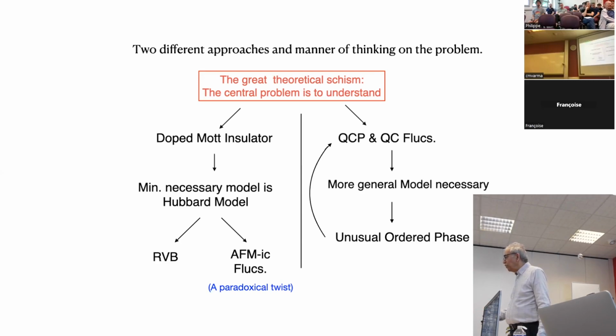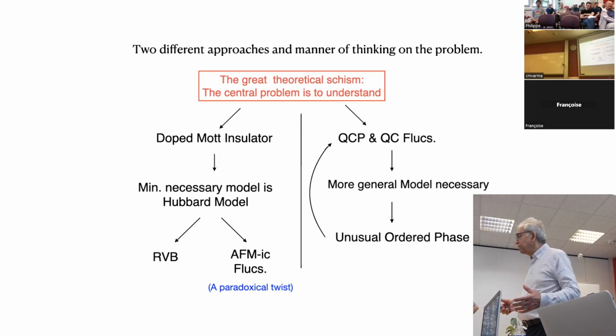And in some cases, it's very easy to see. There's a new material, twisted tungsten diselenide, which has linear in T resistivity, etc. And twisted tungsten diselenide is particularly easy to see because of spin-orbit coupling: the up spin and the down spin are split by about a volt. So the low energy states are all of a given spin at K and opposite spin at K prime, but there is no scattering between K and K prime. That's what's believed, in which case the dynamics is purely the XY model. And that's what's happening. Something similar can be said for twisted bilayer graphene, where they observe this linear in T resistivity.